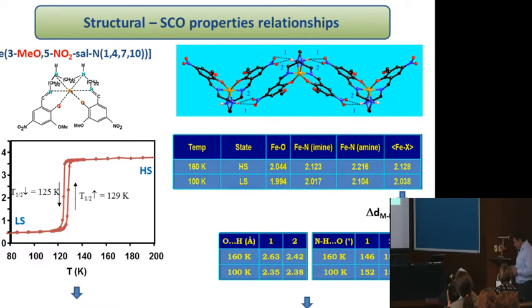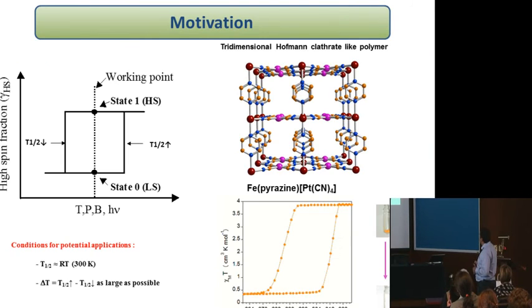This was already described by Azedine. So just so you know, we now know that we have planes with iron here, which are the active centers. And these irons are bridged to other metals, in this case platinum. And these planes are bridged by the presence of this bidentate ligand, in this case the pyrazine molecules. Concerning the property, you already know that we have a very nice spin transition at room temperature, and we can observe here the color change of the samples.